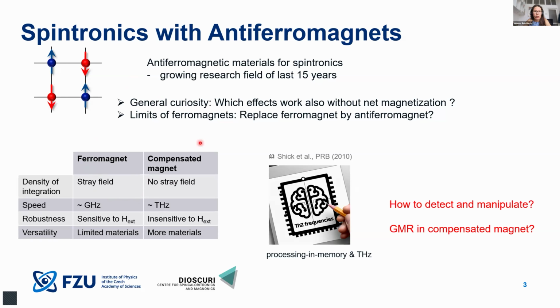And this comes to this very simplified table, which compares the ferromagnets and compensated magnets, some of the fundamental properties of these classes. We all know that there is the stray field present in the ferromagnetic systems, which complicates the integration, how close we can put the 2 elements together. However, there are also other aspects. For example, the intrinsic frequencies, how fast we can reverse magnetization, in ferromagnets is limited to the gigahertz regime, which is slower compared to compensated magnets, in general in the terahertz regime. And also the choice of materials, the materials which nature gave us, is relatively limited when we stay in the ferromagnetic regime.